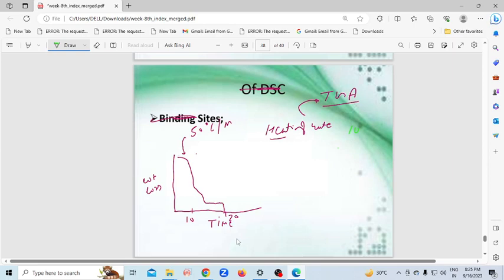Weight loss will occur very slowly, like that. I am not able to draw very clearly, but you can understand. So this heating rate is 10 degrees centigrade per minute. What you understand this way is that when your heating rate was very high, the weight loss is also very fast, and your sample is decomposed in very short time. But when your heating rate is low, 10 degree per minute, it takes more time to decompose. Suppose it is 60 minutes here.